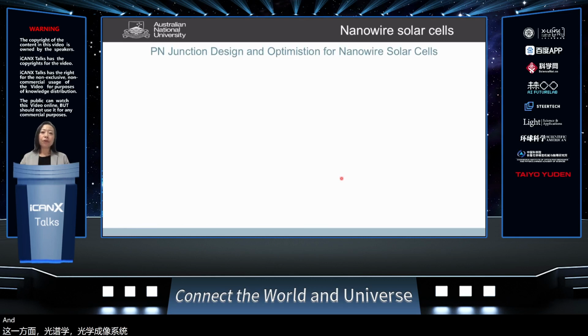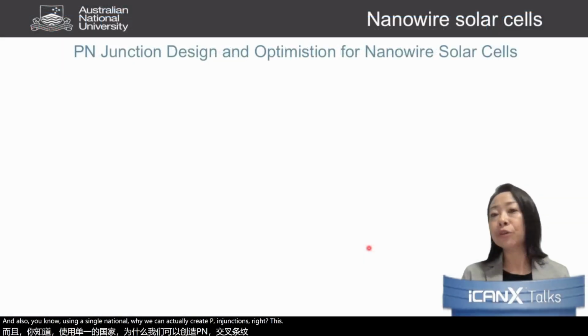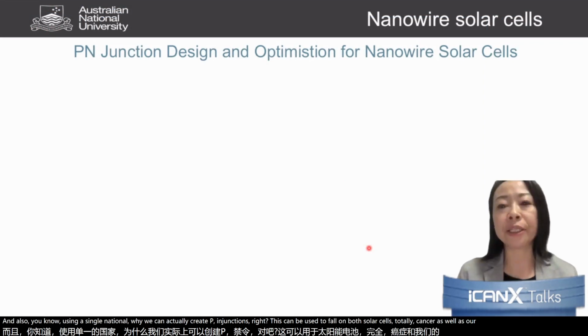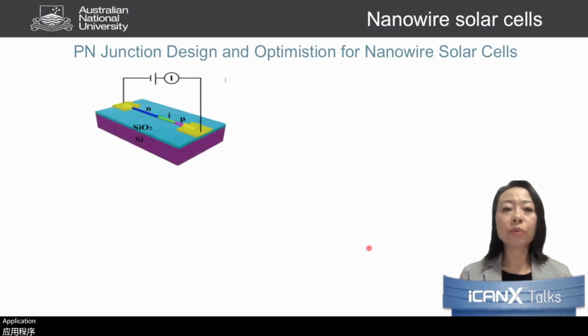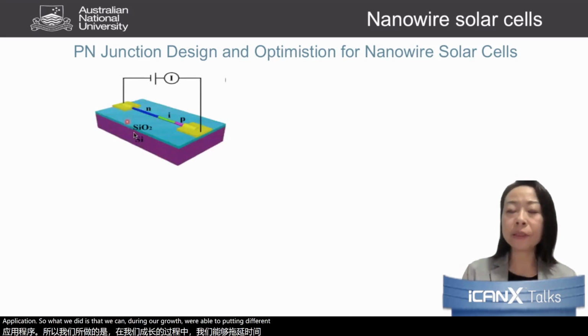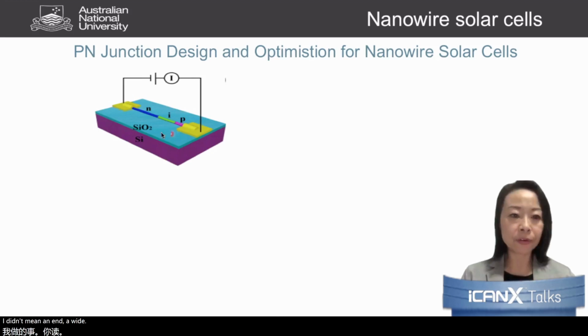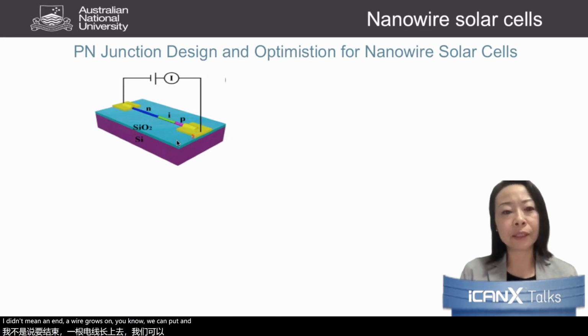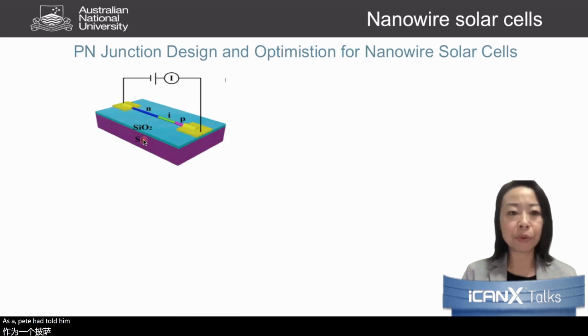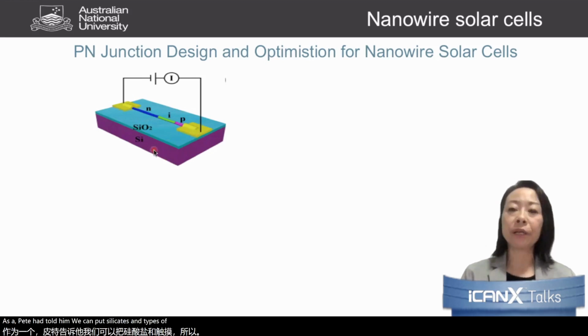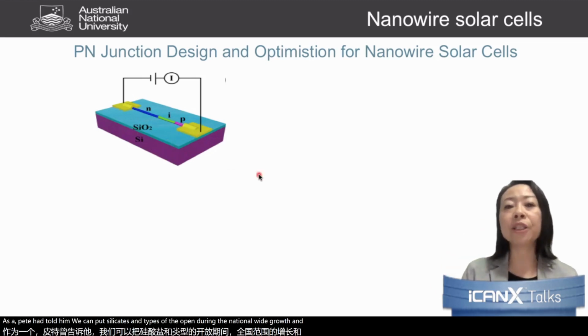And also, using a single nanowire, we can create PN junctions, right? This can be used for solar cells, photodetectors, as well as LED applications. So what we did is that during our growth, we are able to put in different dopants during the nanowire growth. We can put zinc as a P-type dopant, and silicon as an N-type dopant, and create this PN junction.